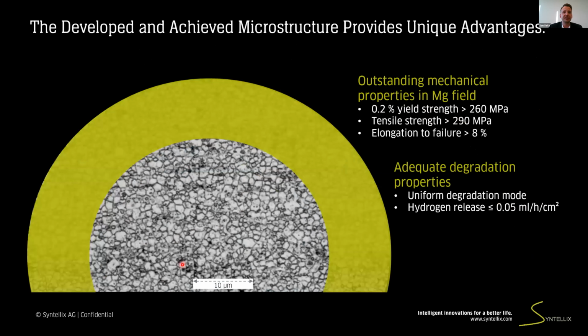The very fine-grained microstructure can be seen in this image. Magnesium provides outstanding mechanical properties: a yield strength greater than 260 megapascals, a tensile strength greater than 290 megapascals, and an elongation to failure greater than 8%. The material degrades in a uniform manner, which results in a hydrogen release smaller or equal to 0.05 milliliters per hour per square centimeter.